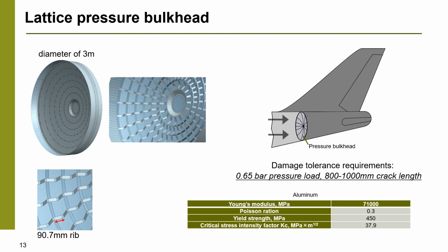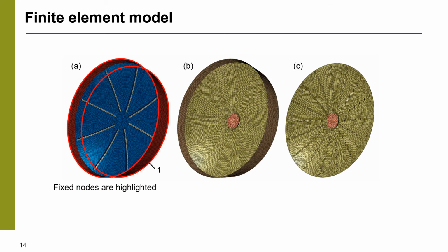So one of the most important critical requirements is damage tolerance. The statement is it should sustain 0.65 bar pressure with a crack length from 800 to 1000 millimeters, and aluminum material is assumed. The finite element model was developed for the analysis of the pressure bulkhead using shell elements, and again